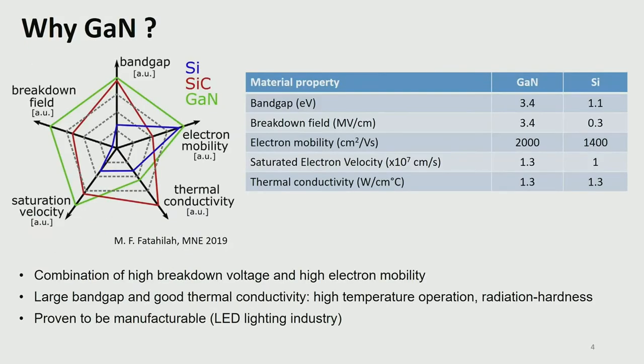So let's start. So why should we use gallium nitride? We can first check the benefits of the gallium nitride in the point of material properties. So if you see the right table, it's a wide bandgap semiconductor with a high critical electric field. It's about 10 times higher than silicon. And also, electron mobility is also quite high. And this combination, high critical electric field and high electron mobility, makes this material very promising for high power or high frequency devices. And in addition to the excellent electrical properties, the thermal conductivity of the gallium nitride is as good as the silicon, which is also very important for devices handling high power.